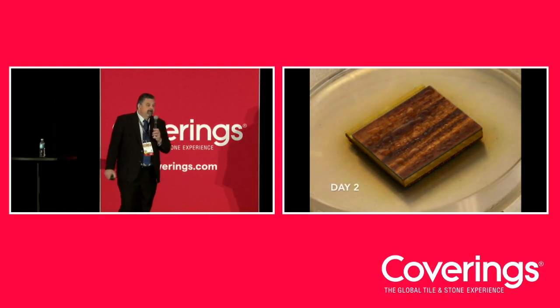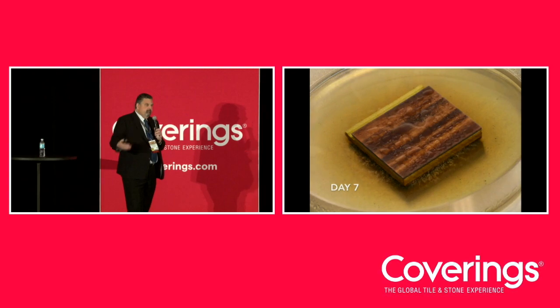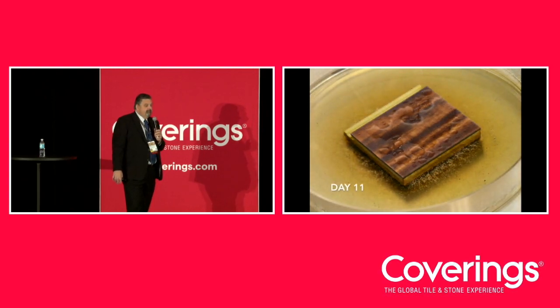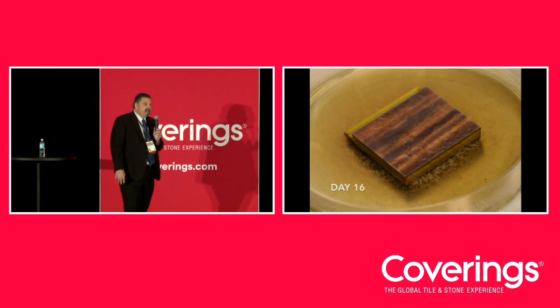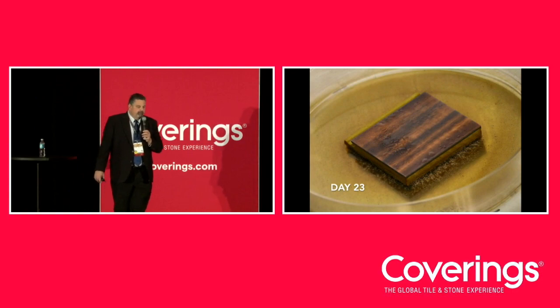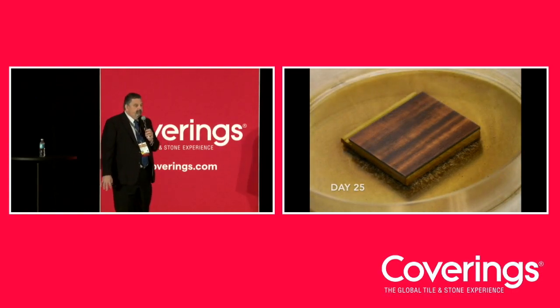Okay, this is a time lapse of a 28-day cycle, which is typical for when you run these mold tests, how long it takes to start to develop. And you can see it's right away, within a week. And you can't get the water out from underneath the system. It's leaked down into your subfloor. So as long as it stays wet and there's a source of food, this mold is growing in your house, and you get furry down there.